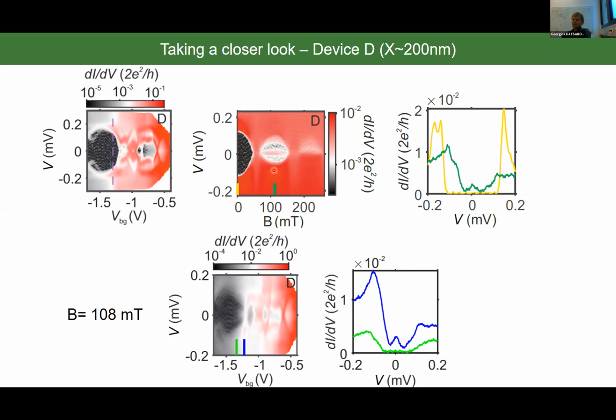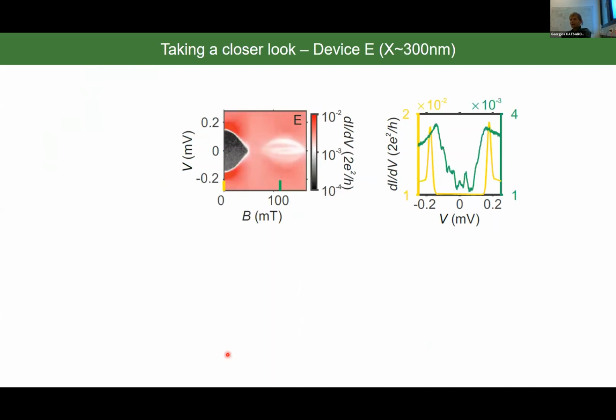If you take now the same plot, but in a magnetic field of 108 millitesla, which now corresponds to the center of the first lobe, again, you can find positions like the blue one, where you would have a zero bias peak, and the majority of the positions would not allow you to see a zero bias peak. And let me finish with our last device, device E, which shows not just a zero bias peak, but multiple lines, additional peaks appearing at subgap voltages.